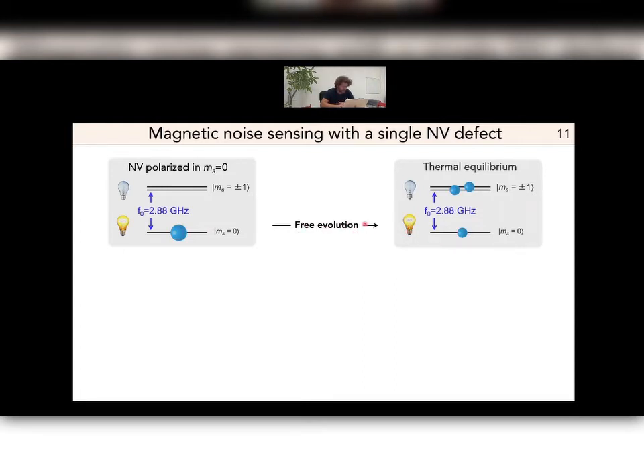The typical time required to reach the thermal equilibrium is called the longitudinal spin relaxation time, T1. What is interesting here is that this spin relaxation time is directly linked to the noise power density at the electron spin resonance frequency. To make it short, if you have some noise at the ESR frequency, then it will boost relaxation, and you will have an enhanced relaxation in the presence of noise.